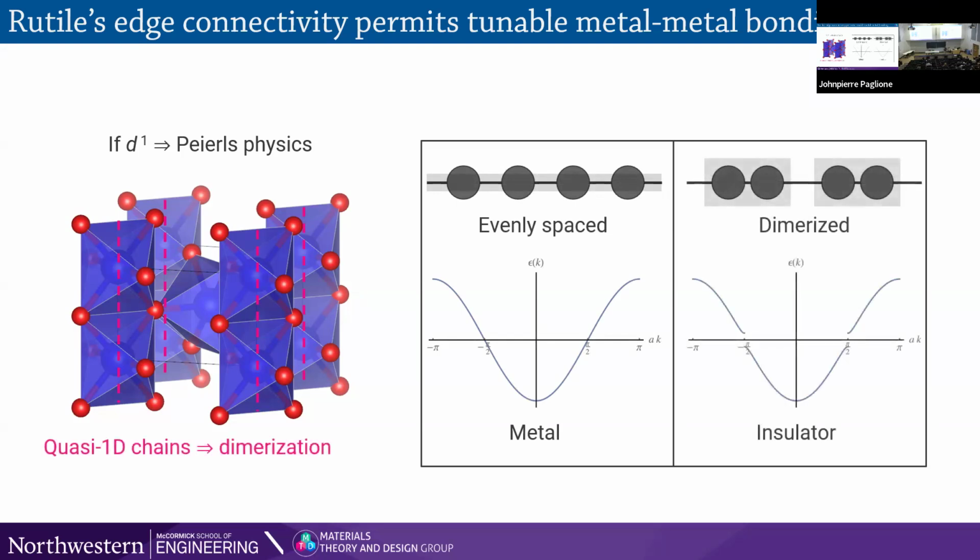And now if you allow the chemical bonding, or that metal-metal bonding that we heard about earlier, this will open a gap at some periodicity, the atoms dimerize. And this is precisely what we want, right? This is the physics of vanadium dioxide. This is the physics of a metal-insulator compound. So how do we realize this in a new quantum materials system?